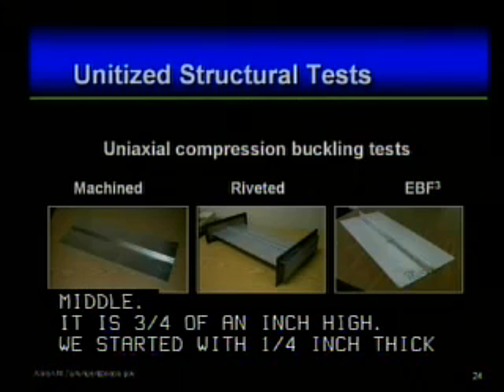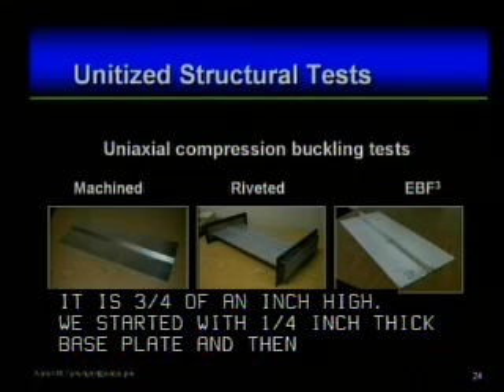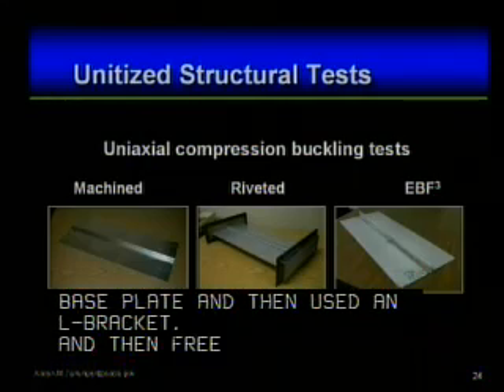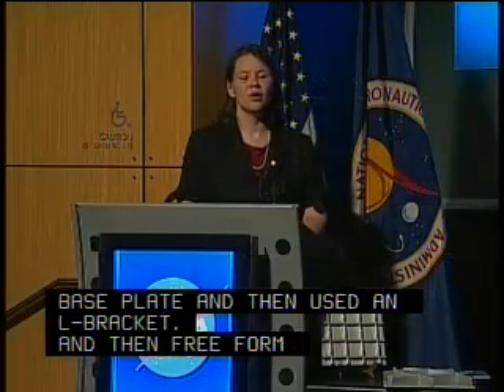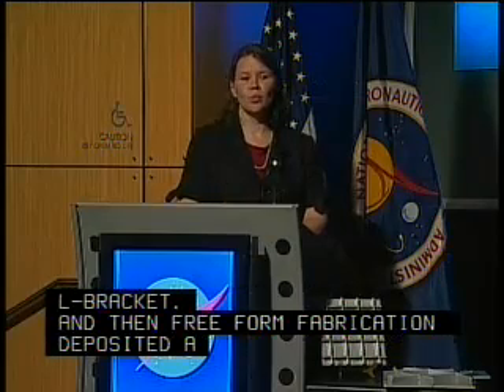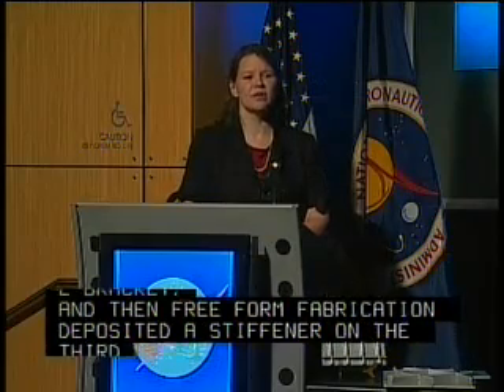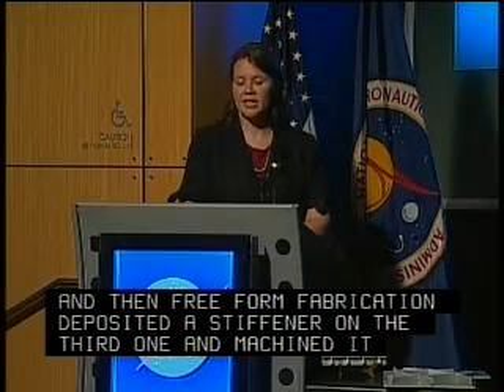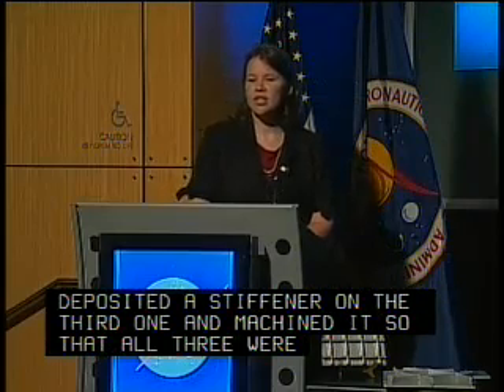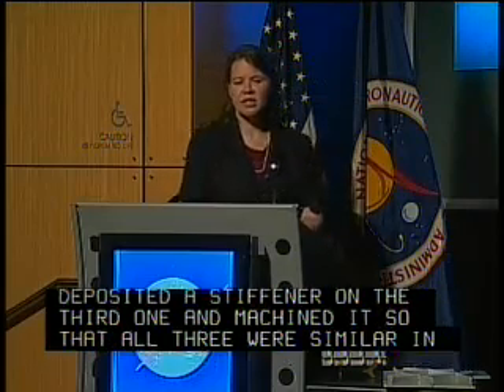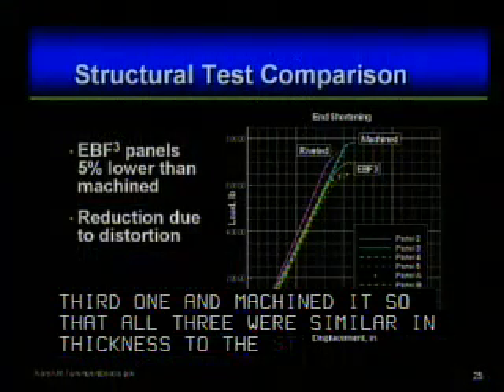And then we deposited a stiffener by E-beam freeform fabrication on the third one and machined it so that all three of them had similar widths or thicknesses of the stiffener. Next slide, please. And this is the compression buckling test. It was tested in uniaxial compression.